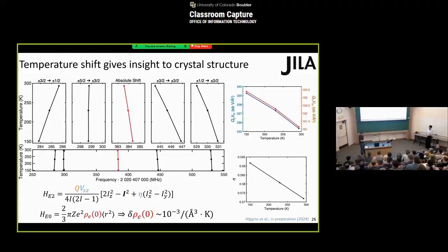Yes, so it's still a difficult experiment, right? Because in the solid state sample, we have 10 to the 15 thorium atoms that we can interrogate in parallel. Now, if you go into an ion trap, then you have a lot fewer thorium ions. So one could imagine building better lasers, with either CW lasers or frequency combs with higher average powers, and one could imagine exciting the nuclear transition in an ion trap as well, but it's still difficult. Thank you.